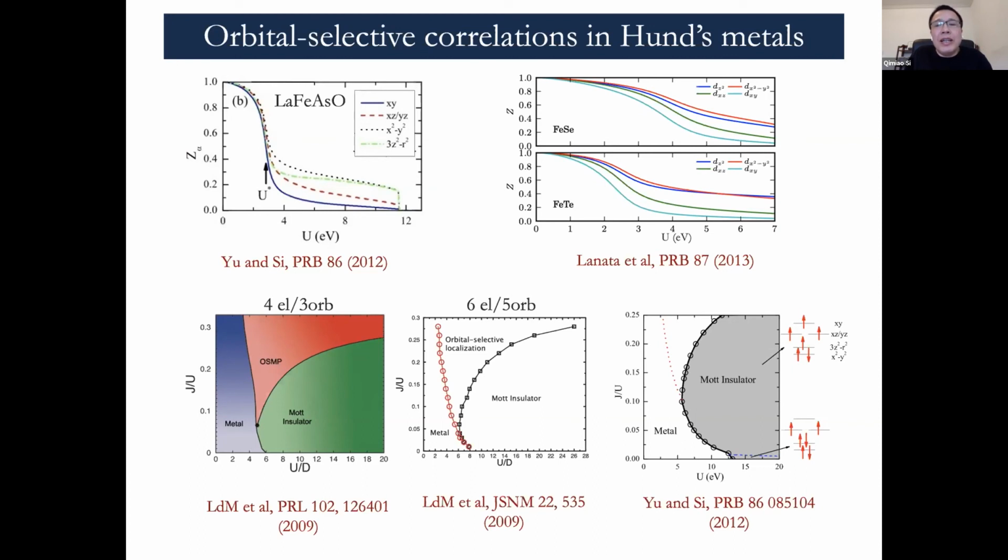If there are lower and upper Hubbard bands, it means charge is as incoherent and localizing as spin is. And we always found that the lower Hubbard band and upper Hubbard band exist. By now, at least in Ming's data on FeSe, that's been checked between theory and experiment. My understanding is that in FeSe, that's also found by ARPES. So to me, U and J Hund's are cooperating, and the lower Hubbard band is really very important, especially in